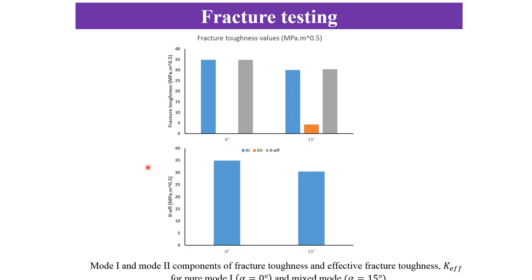The values of mode 1 component, mode 2 component, and the effective value of fracture toughness for 0 degree and 15 degree are also depicted in these two graphs. Here the value of the mode 2 component for 0 degree loading angle is 0, and in 15 degree loading angle, the mode 2 component is significantly smaller than the mode 1 component, as you can see here.